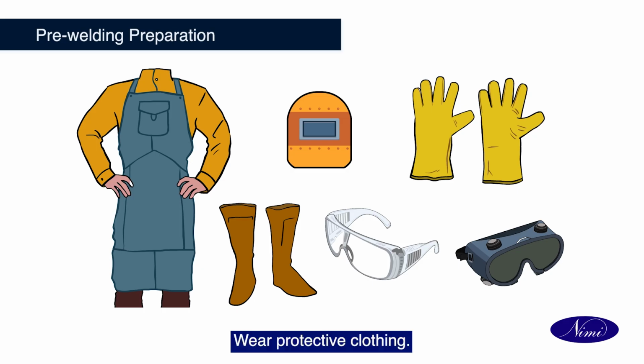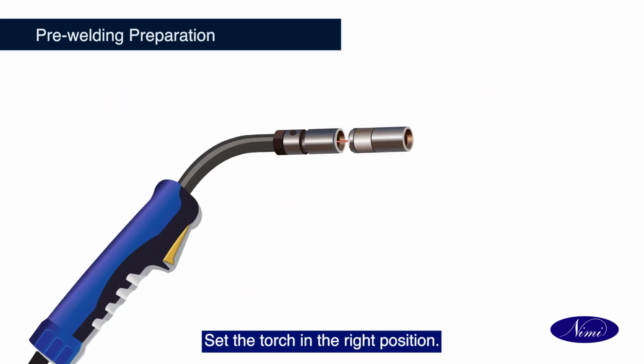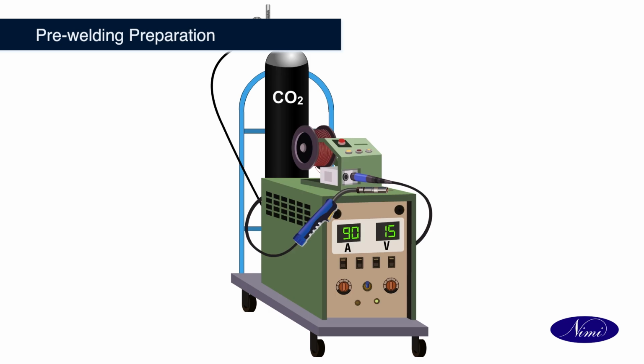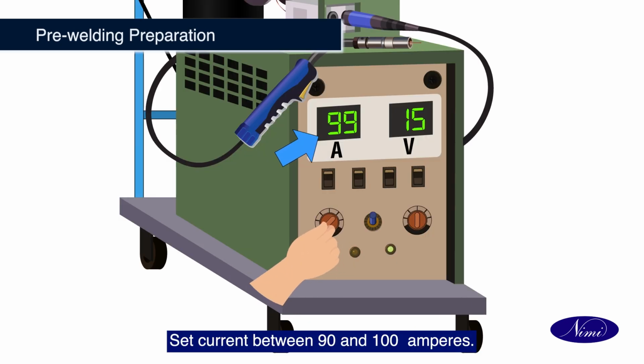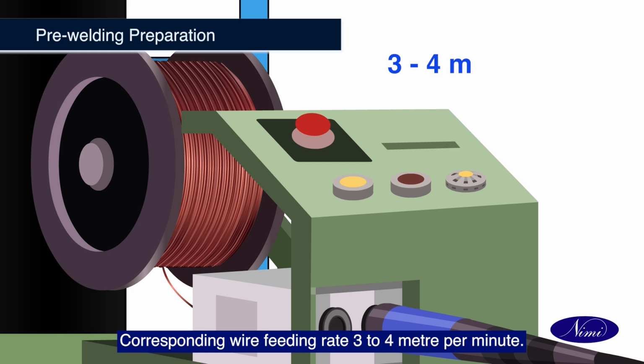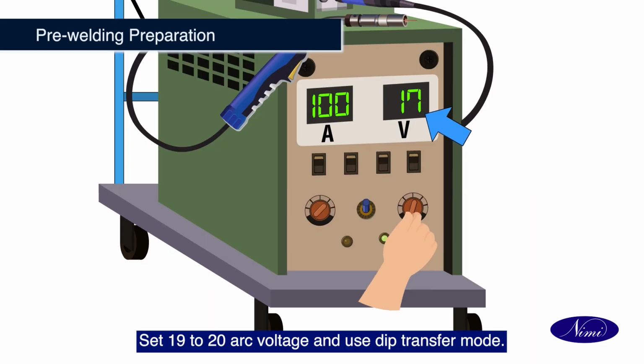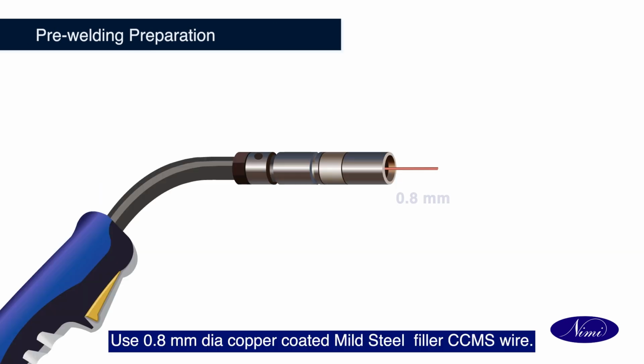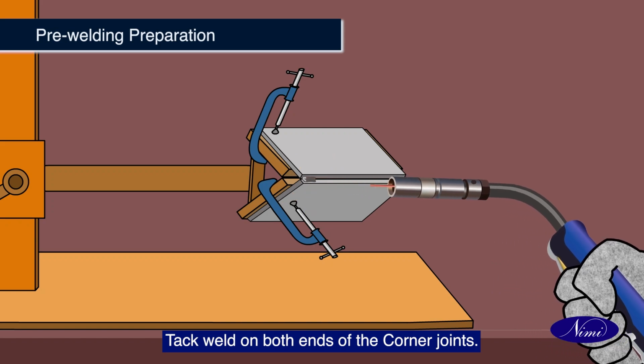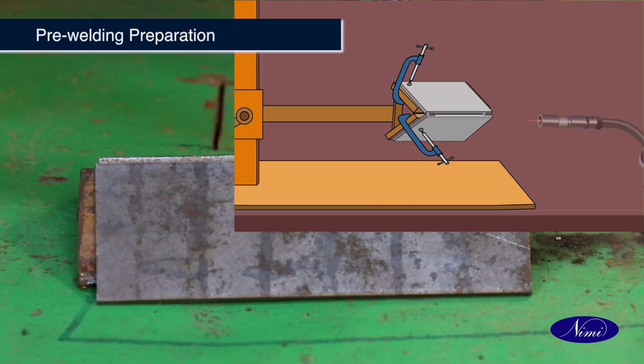Wear protective clothing. Set the torch in the right position. Set current between 90 and 100 ampere. Corresponding wire feeding rate 3 to 4 meter per minute. Set 19 to 20 arc voltage and use dip transfer mode. Use 0.8 mm dia copper coated mild steel filler CCMS wire. Tack weld on both ends of the corner joints.